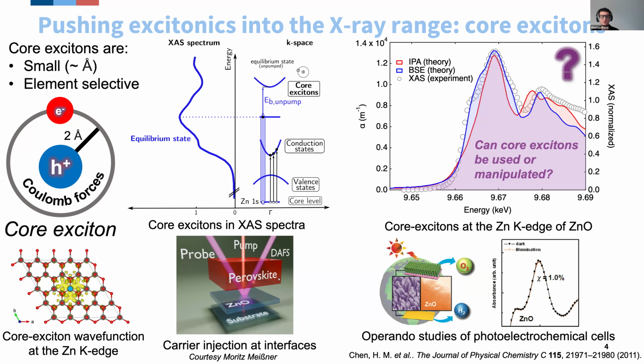So you could think of an experiment where you, for instance, have a perovskite photosensitizing layer, you excite it with a laser, and an electron is injected into the zinc oxide, and now you probe the zinc oxide at the zinc K edge, for instance, and something is going to happen to the spectrum of zinc oxide that's directly related to the interaction between these injected carriers and core excitons. And beyond these studies, there is also a wide field of operando studies. I've seen this many times in the literature, people doing experiments where they record X-ray absorption spectra of materials in the dark or under illumination of optical light, compare the two, and they are able to infer that, well, there are carriers being injected at interfaces, or there is a change of density of states, many different things. But our understanding of this experiment, I believe, could be improved if we can better describe how core excitons actually work and how they interact with free charge carriers.